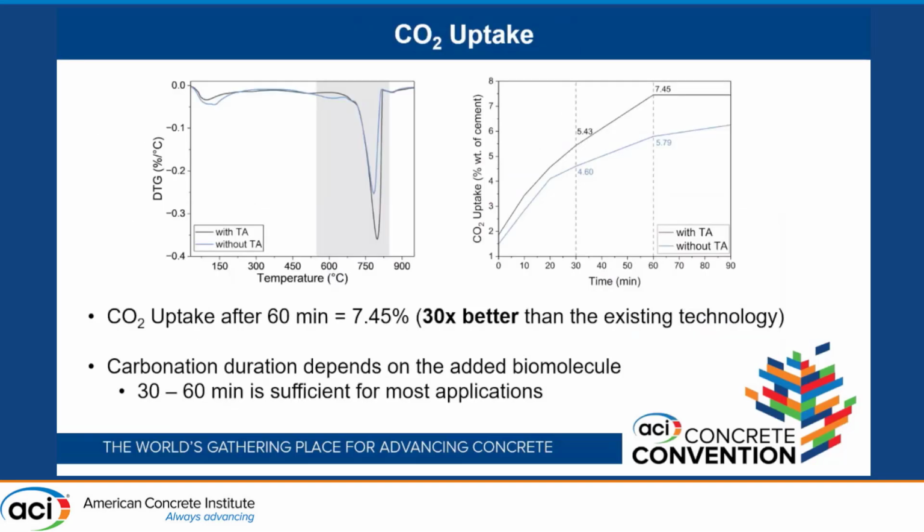Now, looking at the CO2 uptake after just 60 minutes of carbonation, we can see that the CO2 uptake goes up to about 7.5% weight of the cement.